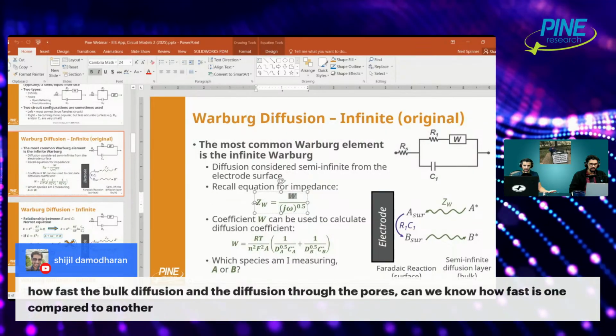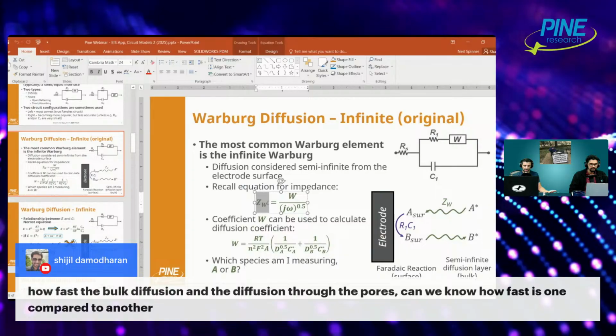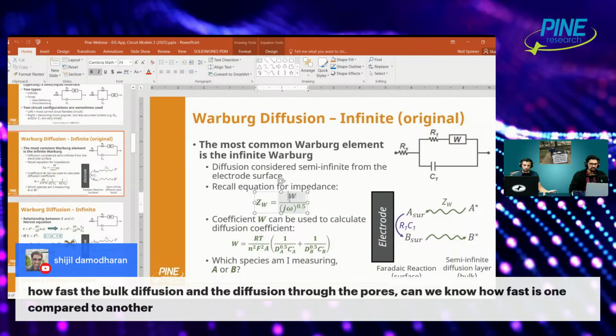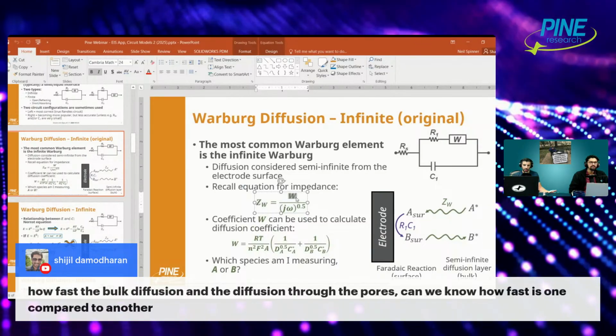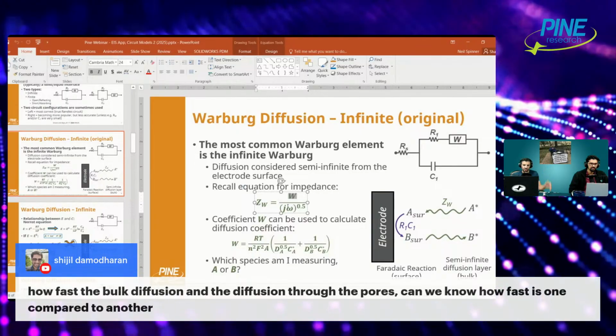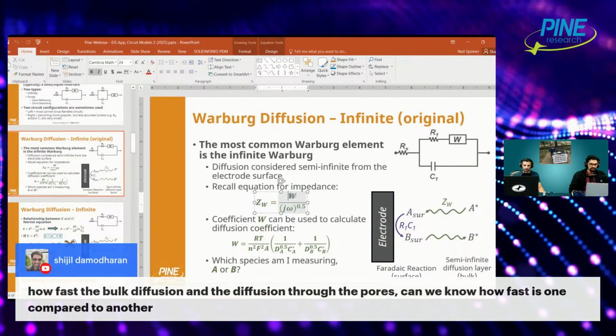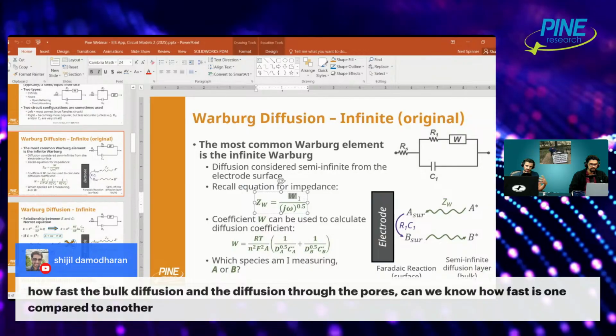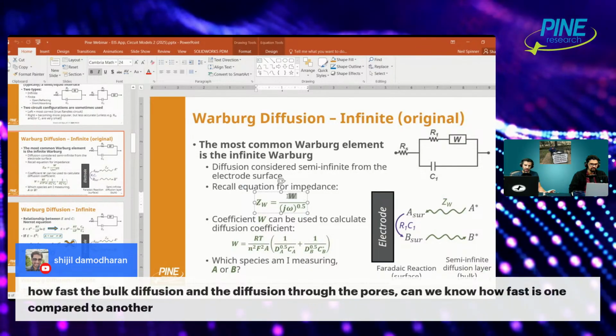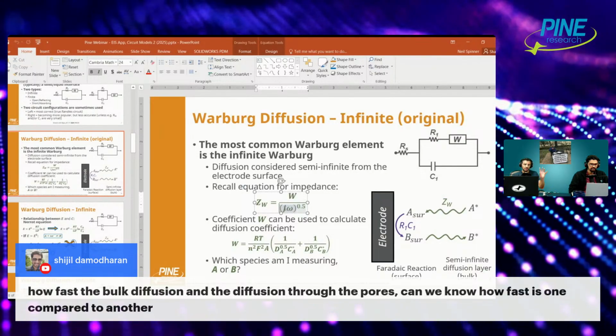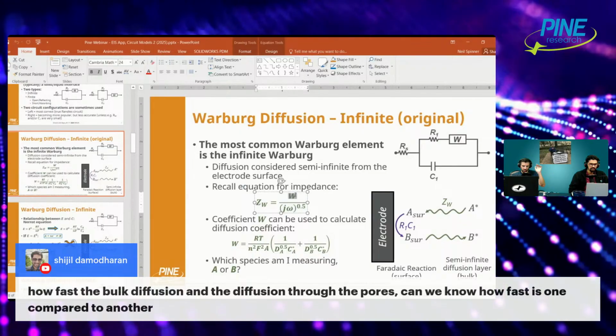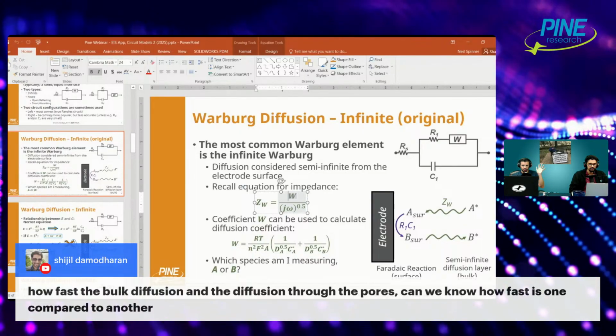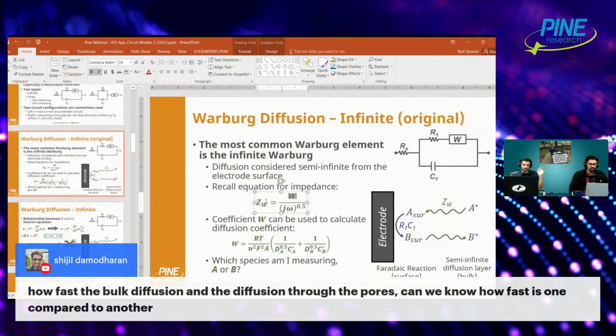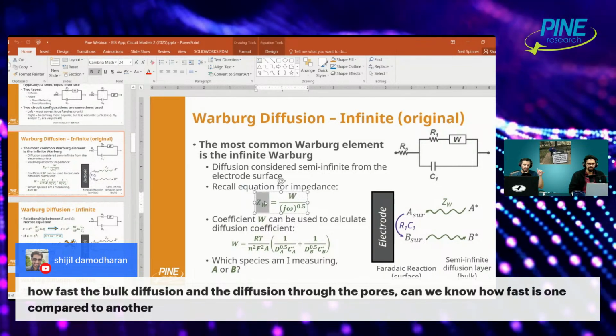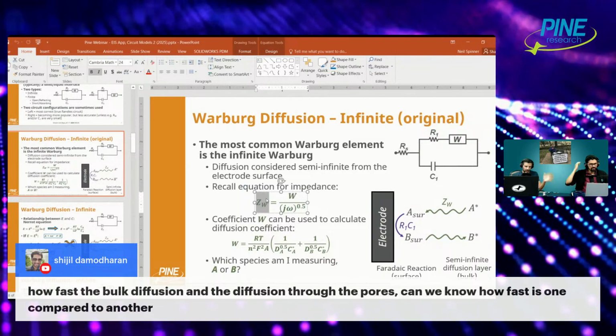Perhaps you could see, even just statistically, it's the ZW here, but it's also proportionate to the W. So you could look at the Warburg constant, for instance, and if the Warburg constant is in the numerator, the way this is, it might be inverse. So you have to be careful what you're looking at. Some software have this in the denominator, so be careful. What I'm showing you is in the numerator. You could, for instance, say the bigger the Warburg constant, the bigger the Warburg impedance, and therefore the worse it is, so to speak, whatever.